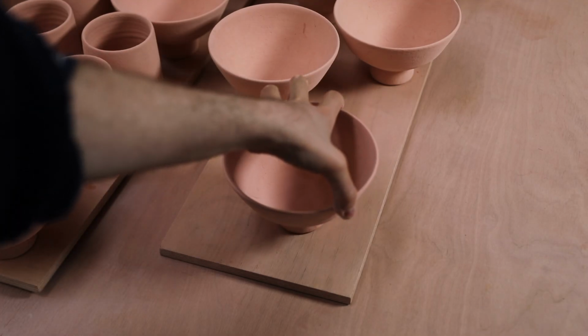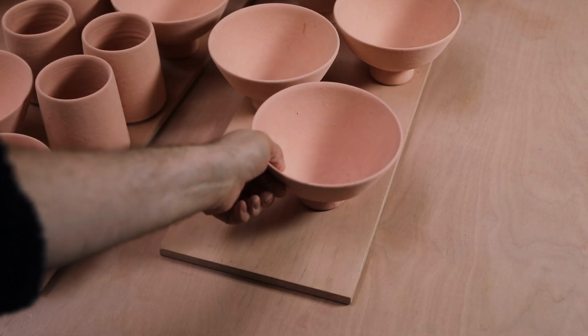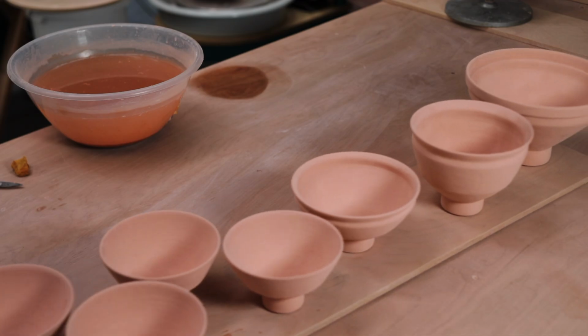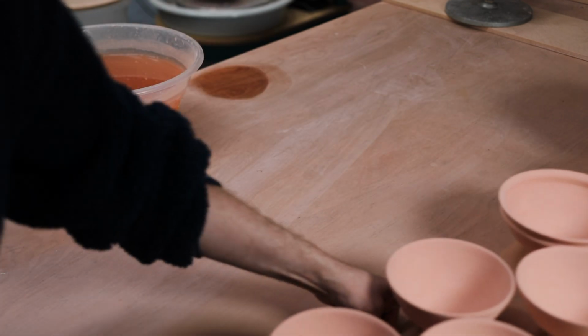and with all of these bowls now glazed and tidied up, once I've accumulated enough work, it can all be packed into my Rohde KG-340 gas kiln. This is a front-loading kiln that's fueled with mains gas, and the firing typically takes about 8 hours from beginning to end. Unlike the firing you saw me pack earlier, when loading the pots inside here, they can't touch, otherwise the glaze coating the pots melts and sticks together, fusing them.